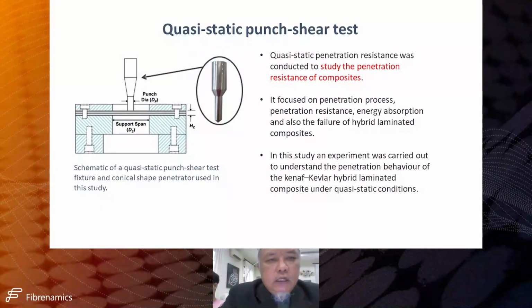Okay, we carried out a quasi-static punch shear test to study the penetration resistance of composite in terms of static load. It focused on the penetration process, penetration resistance, energy absorption, and also the failure of hybrid laminate composite. In this study, an experiment was carried out to understand the penetration behavior of Kenaf Kevlar hybrid laminated composite under quasi-static loading. So this is one of the tests that we carried out.